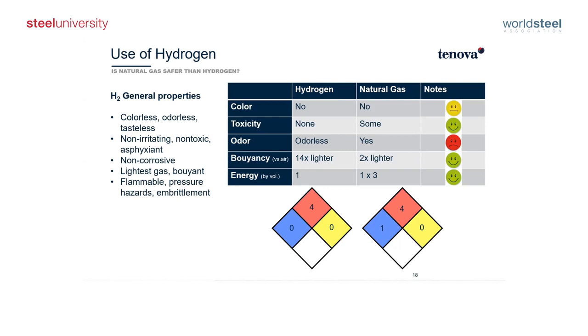And the buoyancy of hydrogen is way higher than the buoyancy of natural gas. This means that in case of a leakage, hydrogen disperses way faster than natural gas does. On the other hand, hydrogen is known under some conditions to cause embrittlement in the vessels and tubes used to contain it, because under certain conditions hydrogen tends to diffuse into the metallic matrix, changing the mechanical properties and causing stress corrosion.